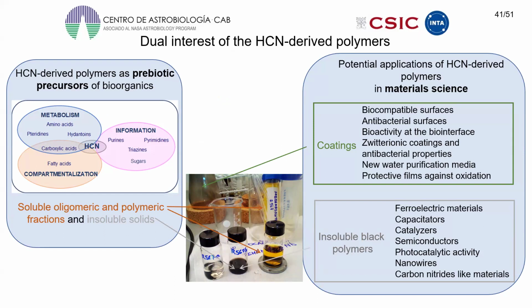In the prebiotic synthesis that I have explained, both the soluble and the insoluble fractions are analyzed. But also, in this type of experiment, a third phase is observed. This is a film that is attached to the walls of the reaction vessel. This property of the hydrogen cyanide derived film was first taken into consideration by Thissen for the development of protective coatings with potential biomedical application.